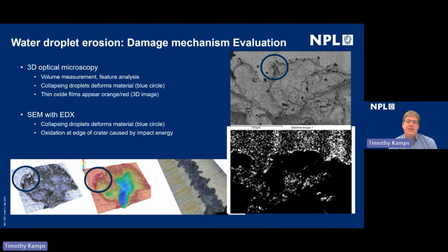So subsequent to testing, we can then look at the mechanisms that are occurring on the surface with different surface analytical techniques. The ones that are shown here are actually ones that we have inside the Advanced Engineering Materials group. Here we're using 3D optical microscopy. So this is using a variable plane 3D optical microscope to evaluate the surface topography of the area that's been subjected to water droplet erosion. We can make volume measurements and identify features.